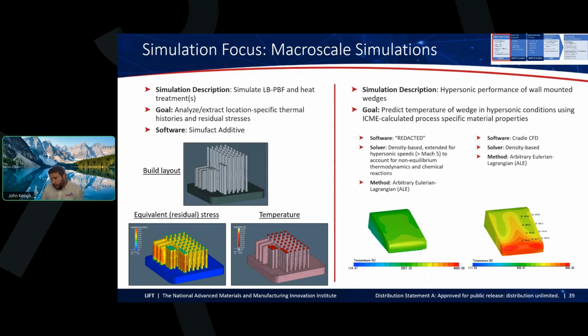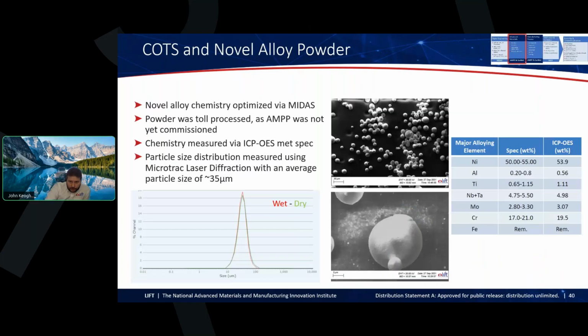But the code on the right actually had great agreement with our empirical measurement in the live tests as far as temperatures and pressures and so on. And then COTS and novel alloy powder, as I mentioned, we worked with a couple different alloy systems. So we benchmarked against the COTS. We also modified the chemistries to be more printable and mitigate some of the needs for heat treatment.